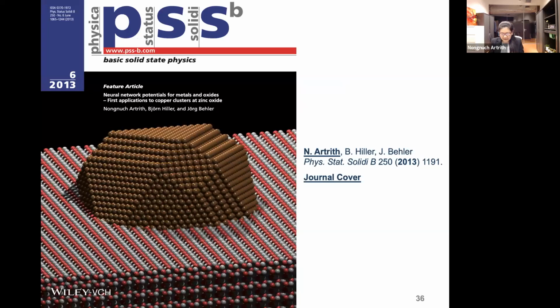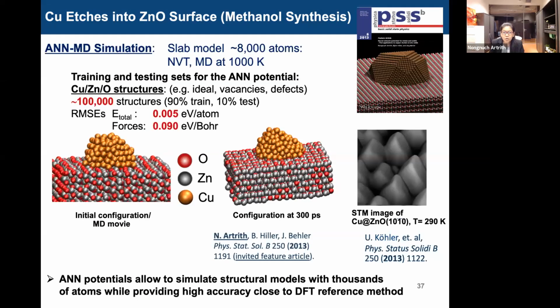So let's see some examples. Back in the Behler group, in 2013, we investigated, for example, copper clusters on a zinc oxide catalyst for methanol synthesis. This system exhibits really strong metal support interactions, and our experimental collaborators were looking for an explanation for their observation. Zinc oxide supported copper is a catalyst for methanol synthesis, right? Actually, it is known that the copper shape change is really different depending on the environment, like the gas exposed in the synthesis condition, for example.